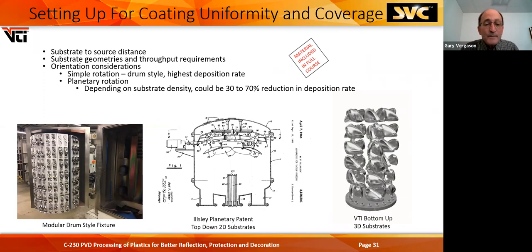The fastest coating that you can put down is a simple drum style over here on the left. Part just rotates by the sputter sources. But when you're in a planetary operation, that can reduce your deposition rate 30 to 70%. So you're going to have to coat longer to get all those parts done, but you're doing more parts in one cycle. And then the picture in the middle is Rolf Isley's planetary patent from a long, long time ago, 1964.